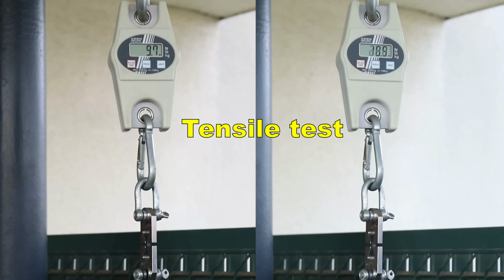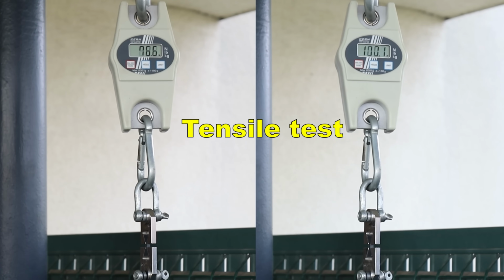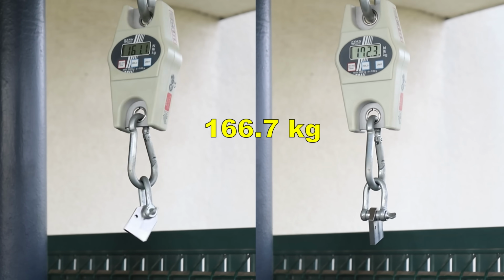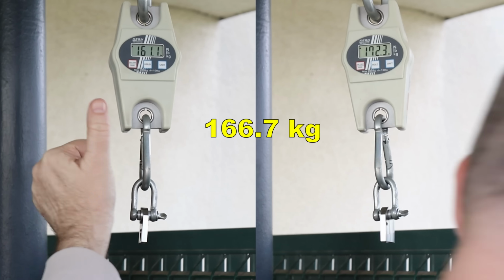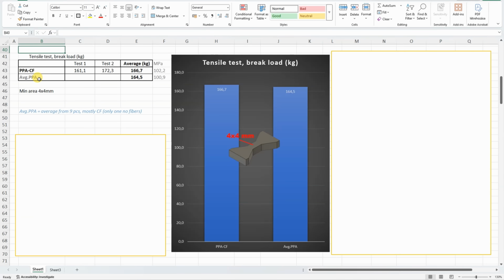Let's start the mechanical testing. Tensile test with horizontally printed objects. Again, for the better reference, I will include the data for the average PPA, which I calculated from 9 pieces from that summary table, and only one doesn't have fibers. And we can see that the tensile strength is extremely similar, but in both cases this is very strong compared to any other filament type.